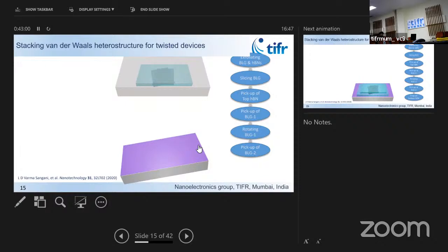If this is 1 layer of graphene, I can have it directly aligned, or I can rotate it, or tilt. It's an interesting question. No, it's as flat as possible. There can be some imperfections inside the system, like a trapped bubble or air gap in between 2 layers, but they're flat because we eventually let go of them. Initially we bring them in contact with pressure, but after that we do a lot of processing. That would actually be an interesting experiment, but we don't have a way to control the tilt.